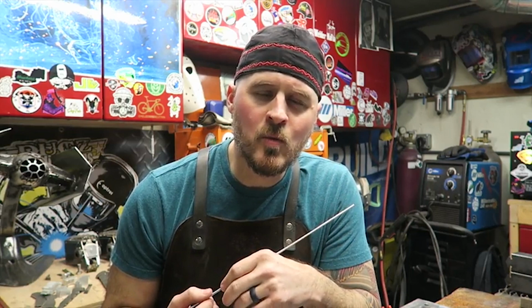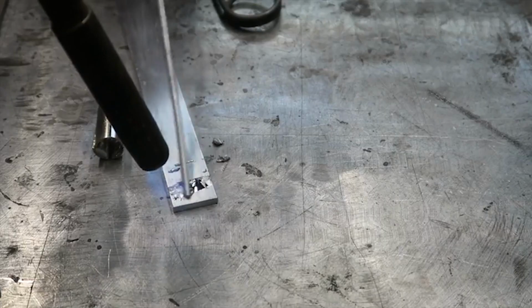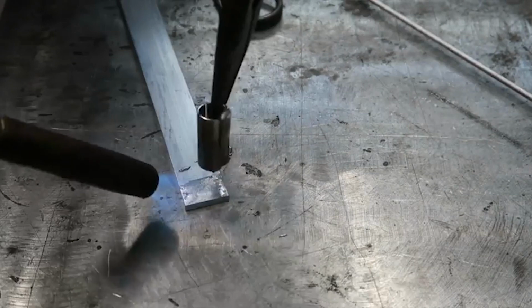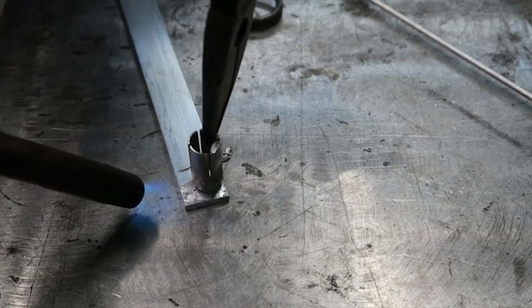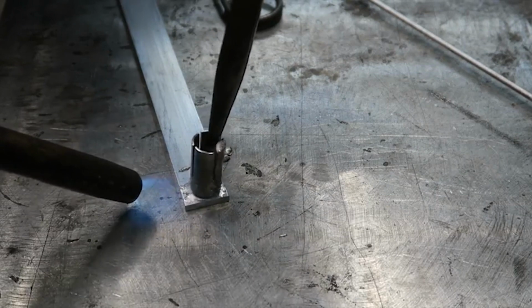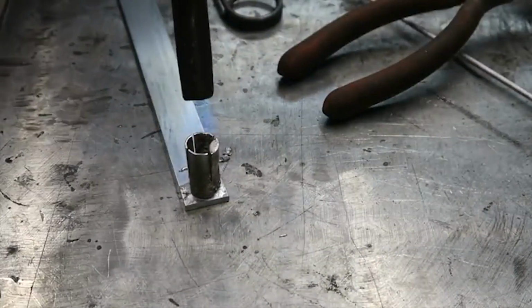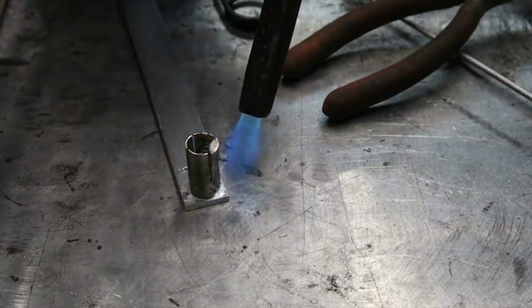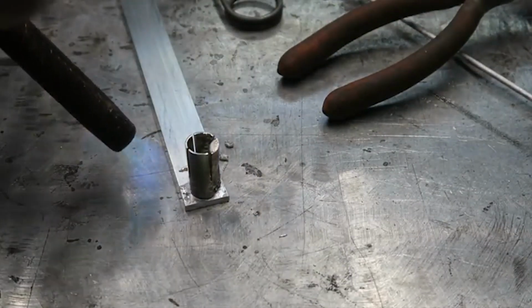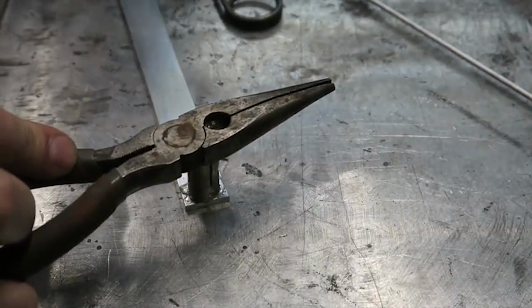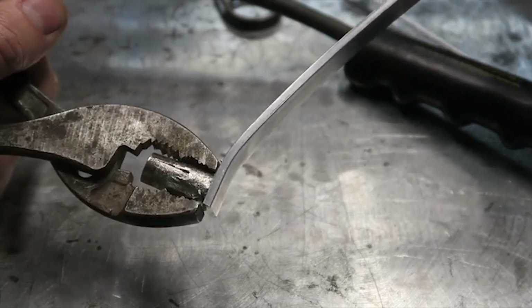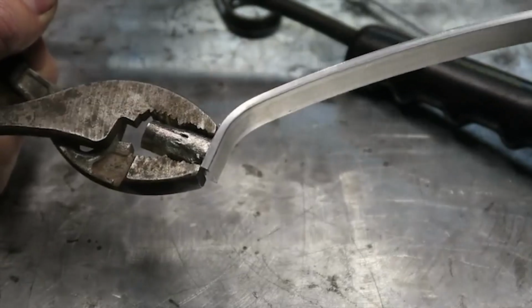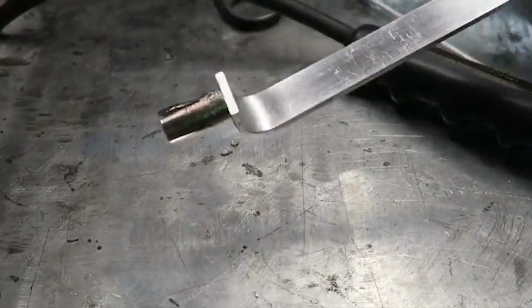To give you an idea of the tensile strength of this brazing rod, I'm going to braze this small aluminum bushing to this 1/8" aluminum flat bar. The first step always is cleaning your material and then gently heating up the base material until you tin both surfaces. Once both surfaces are tinned, set the aluminum bushing on top of the molten puddle, heat up the surrounding area until things become fully liquid, and then apply a light pressure while everything solidifies. Performing a quick bend test after things cool down, you will see the material bends before the braze itself fails.